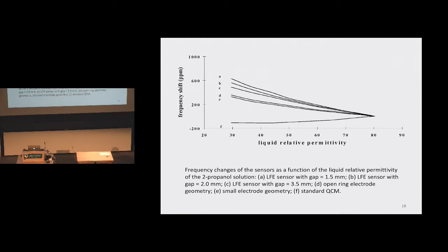We then continue to ask the question, well, what about another electrical property? And that electrical property is permittivity. Those of you who are familiar with dielectric constants realize that's a dielectric constant of water. And as you add 2-propanol solution to that, what happens is you get a change in the permittivity. Here what you see is the standard QCM represented as F. And now these three here correspond strictly to the LFE for A, B, and C, and E are the open ring geometry kind of grouped together. And again, you see the bigger changes occurring in the corresponding LFE structure.